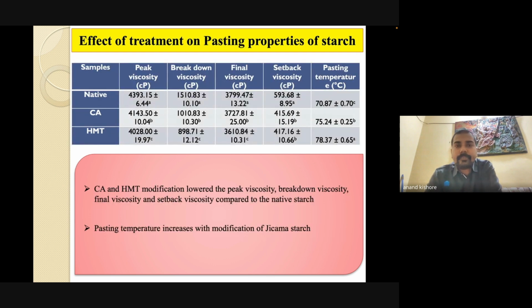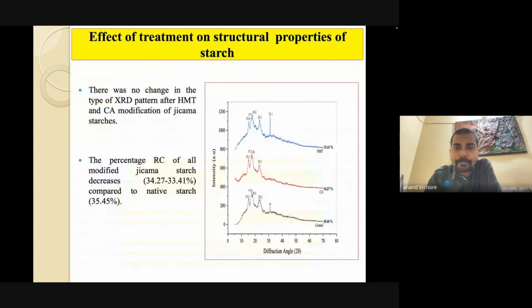Next is the effect of treatment on the pasting properties of the starch. The peak viscosity, breakdown, final viscosity, and setback viscosity decrease after the modification. But the pasting temperature increases after modification. That means there is very good thermal tolerability after thermal processing. In the case of HMT, the value is higher compared with citric acid. It may be that due to the heat treatment, there is some rearrangement of the amylose and amylopectin, so we have a stable structure. That may be why the pasting temperature is high in the HMT treatment.